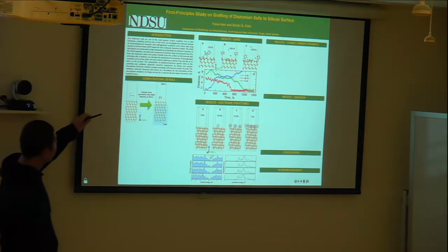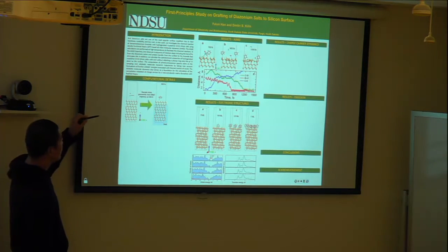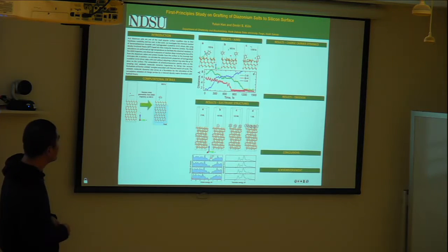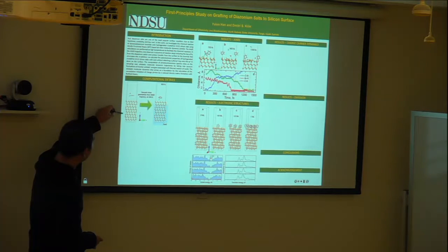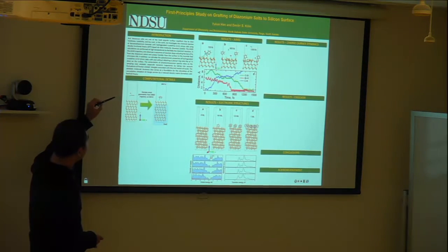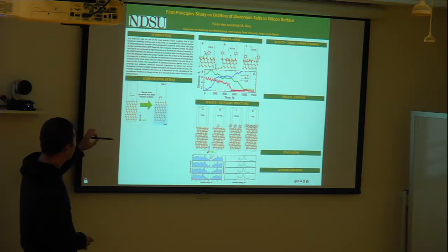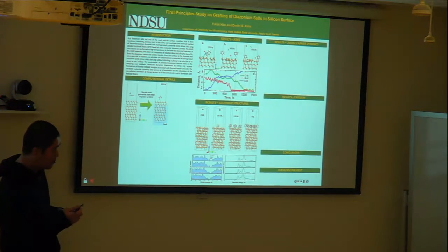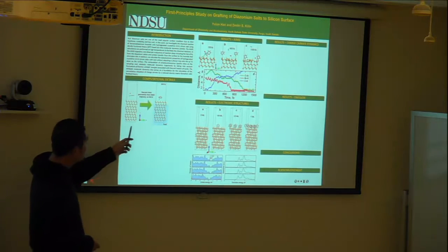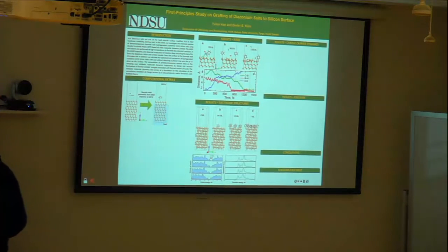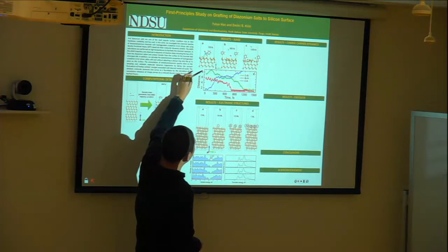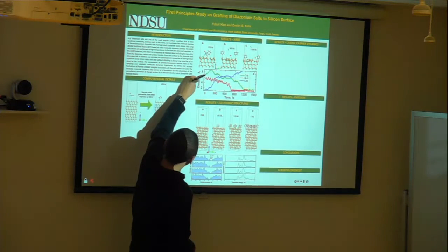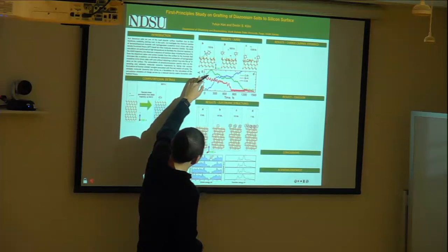So this is my model. To figure out the chemical reaction, we use ab initio molecular dynamics. And this is my geometry optimized model. First we run a high temperature molecular dynamics to sample the trajectory. Here is my result for ab initio molecular dynamics. The blue means the distance between carbon and silicon.